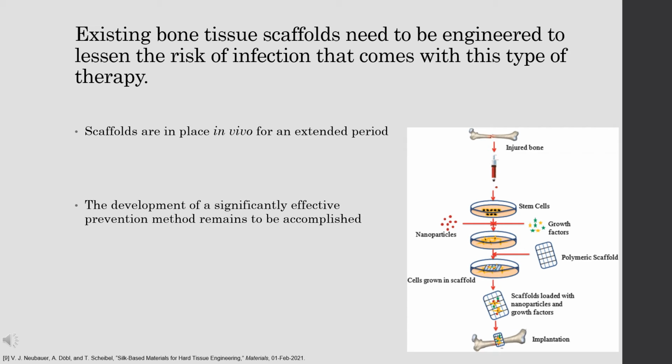In order to fill this gap, existing bone tissue scaffolds should be engineered to fight infection. This could be done by improving the antibacterial activity of the scaffolds or by reducing the time required for regeneration. The addition of silver nanoparticles would be a relatively simple solution and would be added during the preparation of the scaffold. A study was done where magnesium oxide nanoparticles were incorporated into silk fibroin scaffolds to improve hydrophilicity. Integrating silver nanoparticles into these scaffolds could be done in a similar fashion.